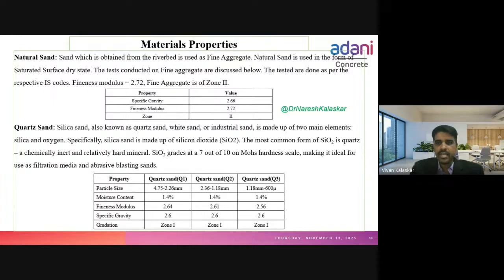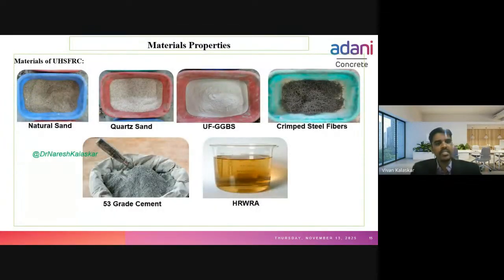These are the natural sand properties. We have taken zone 2 sand and quartz sand. From M80 to M120 we have used natural sand. After M120 we have totally replaced natural sand with quartz sand. These are the material properties of quartz sand. So these are the materials which we have used: natural sand, quartz sand, ultrafine GGBS, crimped steel fibers, 53 grade cement, and high range water reducing admixture.